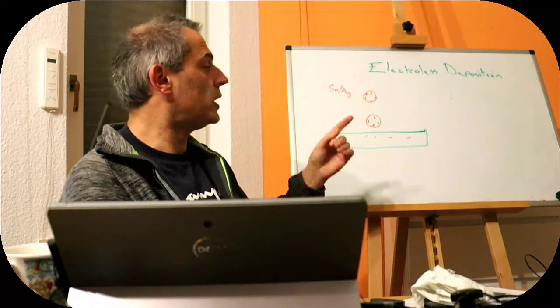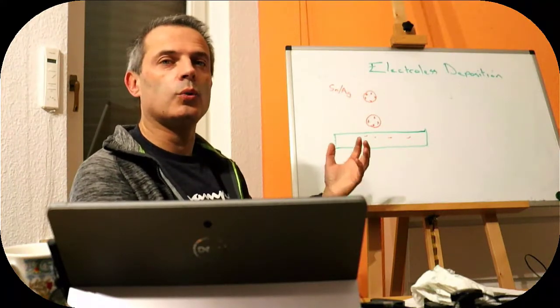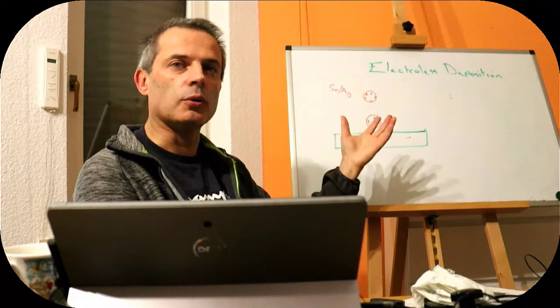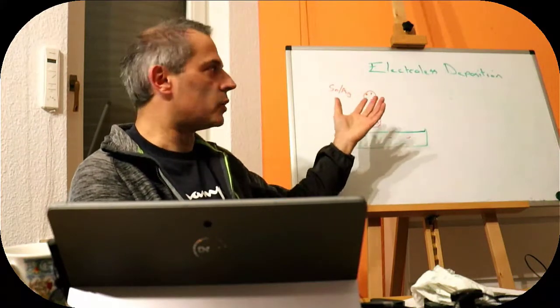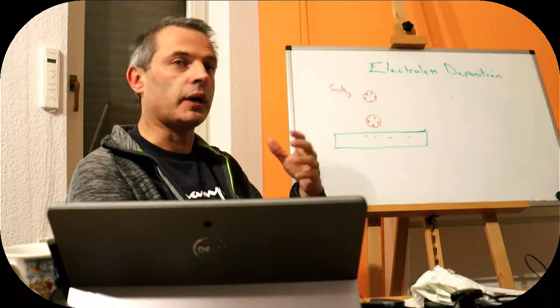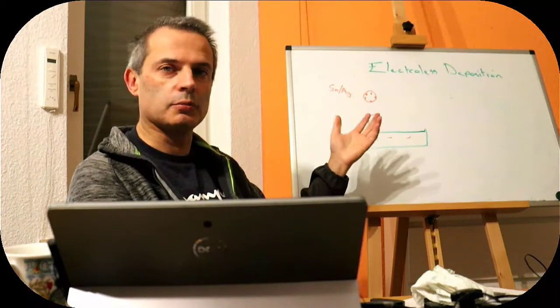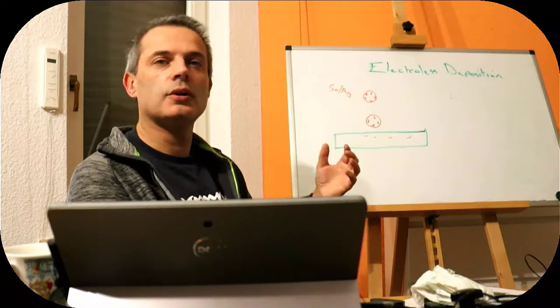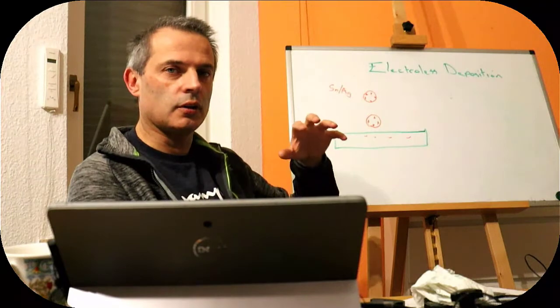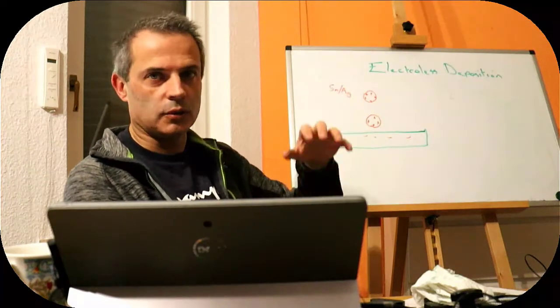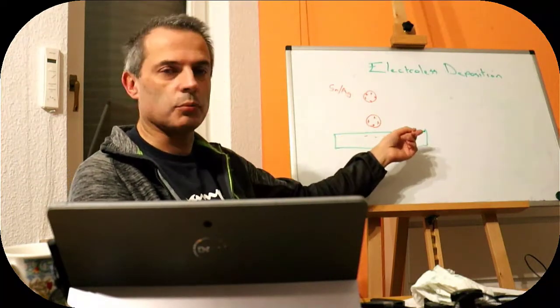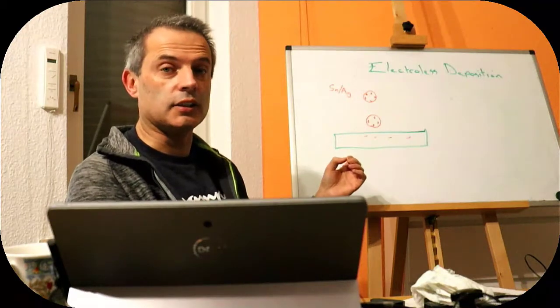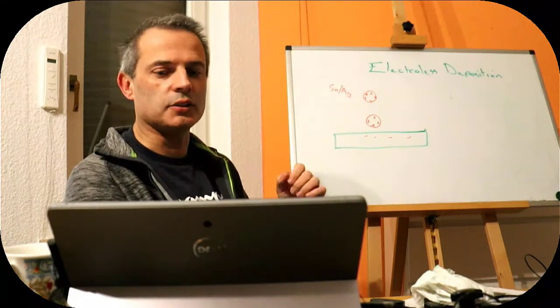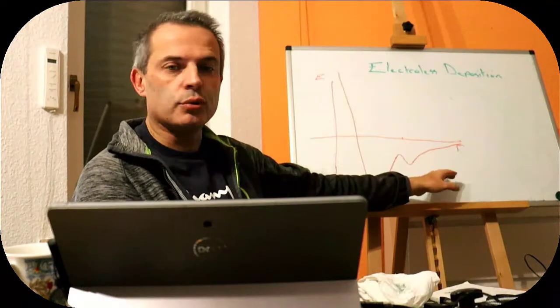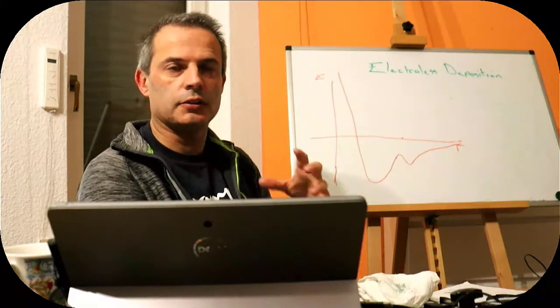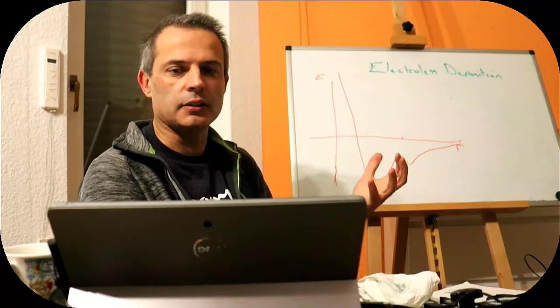If we have a polymer, we have to get to this state beforehand, which takes us back in this course to corona discharge and plasma treatment of polymers, where we can graft hydroxide and acid groups to the surface of our polymer, which will make it negatively charged, as long as we control the pH. This is the approach curve of a positively charged colloidal particle to a negatively charged surface.